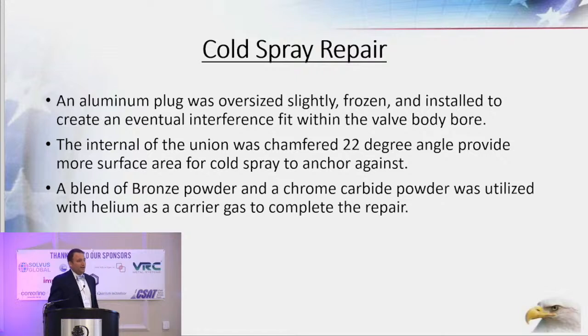Put a little bit of a chamfer on it. This is a quarter inch union. That wall that was sticking up is very thin, so we wanted to have a little bit more of an anchor. So we put a little bit of a profile on the bottom of the union just to give it a little bit more stability. And we used a bronze chrome carbide blend for this, and then we used helium.